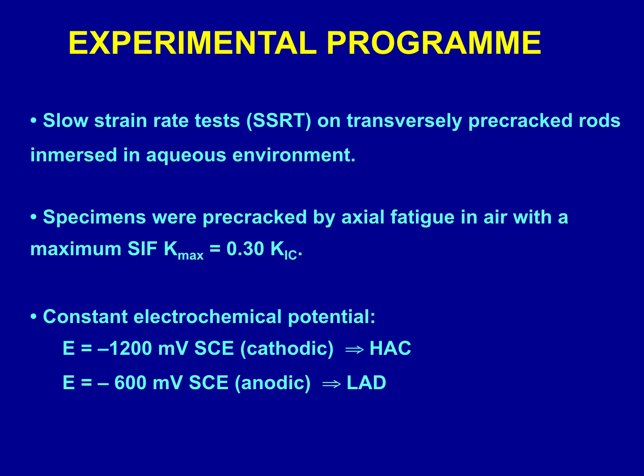The experimental program consisted of constant extension rate tests or slow strain rate tests, SSRT, on transversally pre-cracked rods immersed in aqueous environment. The specimens were pre-cracked by axial fatigue in air with a maximum stress intensity factor Kmax very moderate, 30% of K1C, to avoid plastic effects and overload retardation effects in the close vicinity of the crack tip, and two constant electrochemical potentials were used,